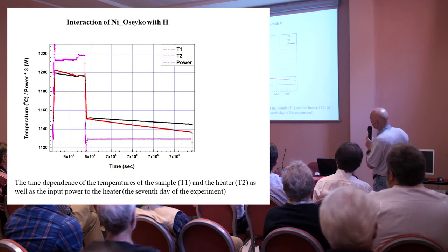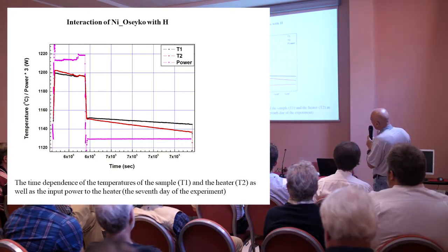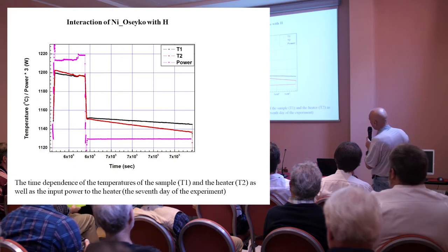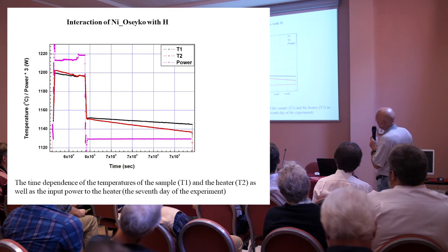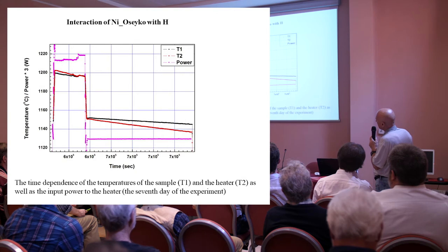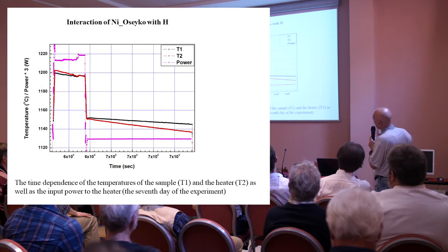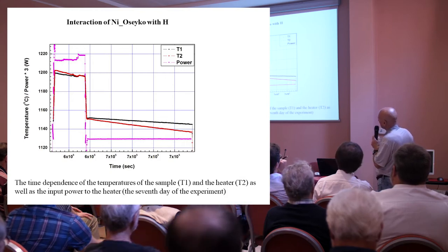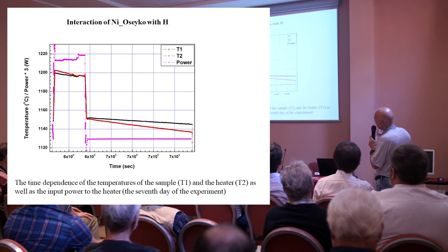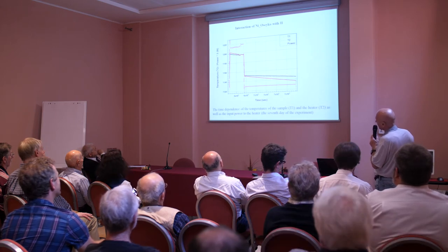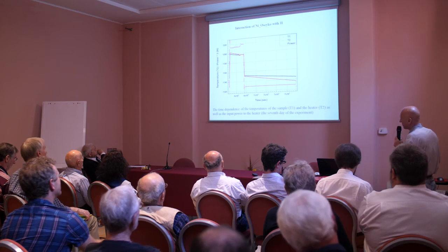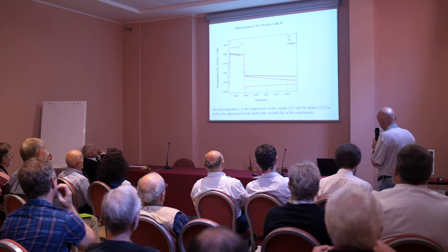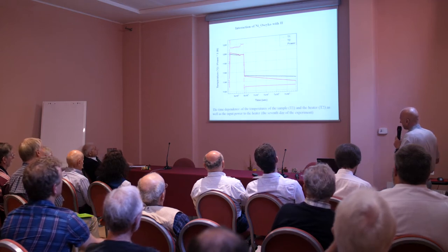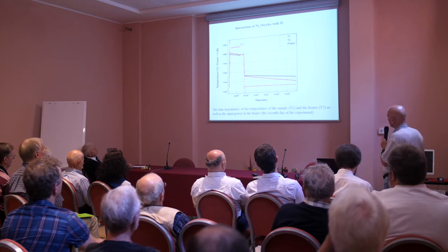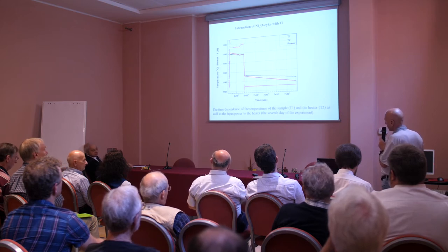And here you see that it's below. Then it starts a little bit higher. Then we change the law of the energy input. Here's the energy input, and then make it constant. And here you may see that as if the temperature of the fuel starts to be higher than the temperature of the heater. But alas, it's an artifact, because you see the input is constant, and the temperature of the heater is decreasing slowly, but faster than the temperature. No, actually, not the temperature, the readings of the thermocouples. It's a K-type thermocouple, nickel aluminum. That was a warning that, in spite of the apparent logic of the experiment, artifact dangers should always be taken into account.